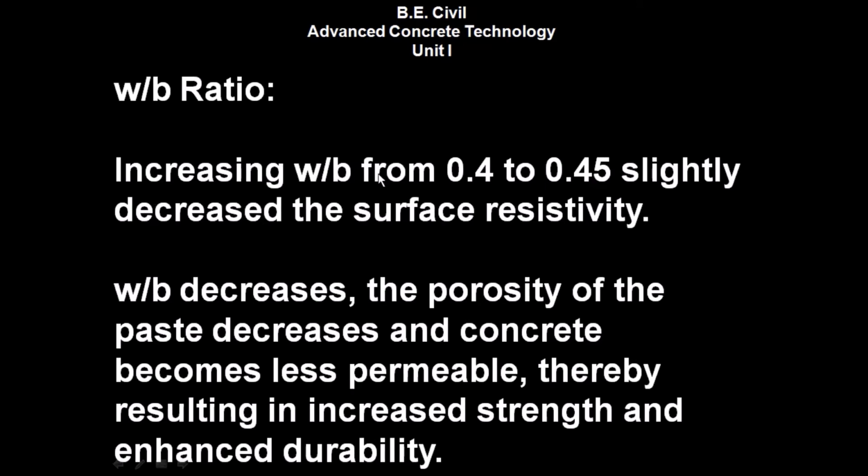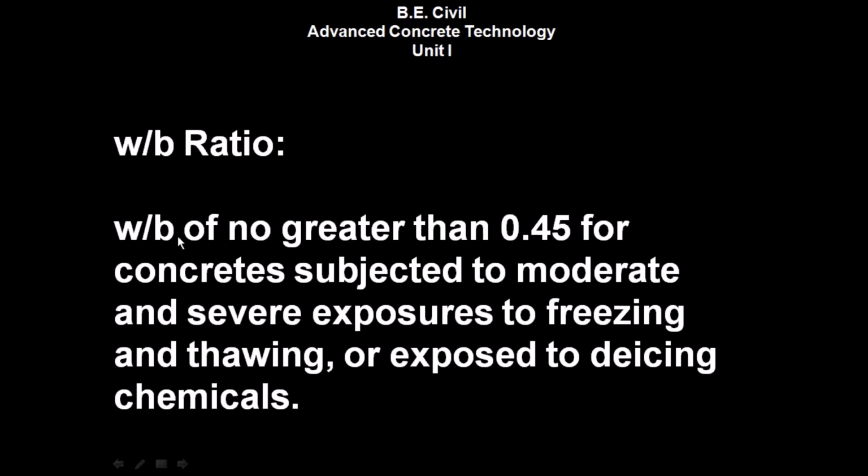Increasing the water binder ratio from 0.4 to 0.45 slightly decreased the surface resistivity. As the water binder ratio decreases, the porosity of the paste decreases and the concrete becomes less permeable, thereby resulting in increased strength and enhanced durability. So a water binder ratio of no greater than 0.45 is recommended for concretes subjected to moderate and severe exposures to freezing and thawing or exposed to deicing chemicals.